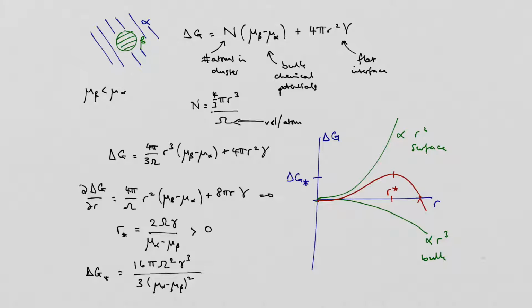Whereas in the spinodal, we looked at the second derivative, and we looked at what wanted spontaneously to happen, and we saw that just the infinitesimal change was still energetically favourable. And under those circumstances, the idea of the interface is not quite so clear what it means.